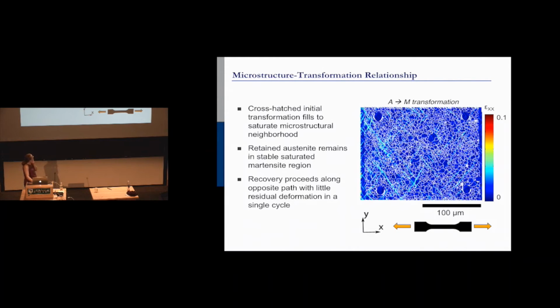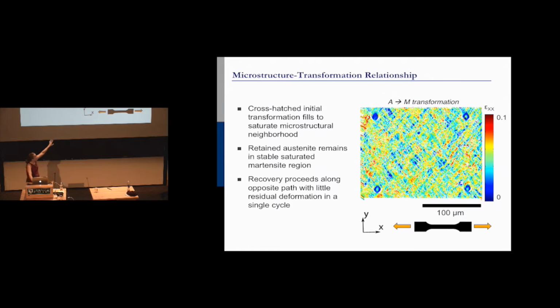So we're pulling, and okay, this is the first thing off the bat. The conventional thinking about this phase transformation was that there was a very sharp interface. And right off the bat, we didn't see this. So these are, as far as we know, the first direct observations of what happens in phase transformation on the microscale as it progresses through grains, across a wide view of grains. There have been TEM studies, but there hasn't been this length scale. And so people thought that there was a very sharp interface. And right off the bat, we see a very crosshatched interface. It's very diffuse.